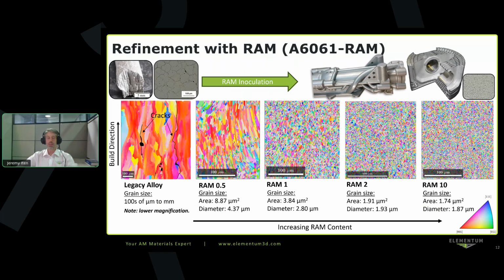At this point, we've completely eliminated any solidification cracking problems and drastically improved the properties. And a RAM 2, we've standardized many of our products around a RAM 2 because it provides a fully refined microstructure. You can see under 2 microns average cross-sectional grain diameter, and good isotropic properties. You can also move to higher RAM contents like a RAM 10. For RAM 10, you don't get a lot of further refinement. You're already pretty much fully refined by a RAM 2.